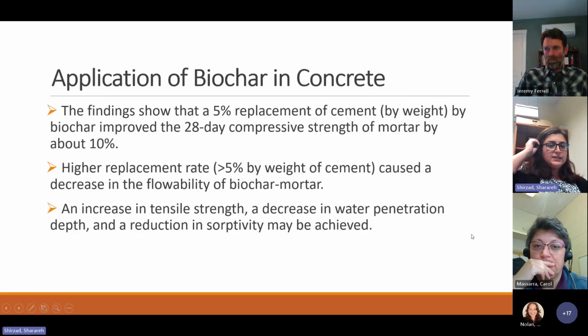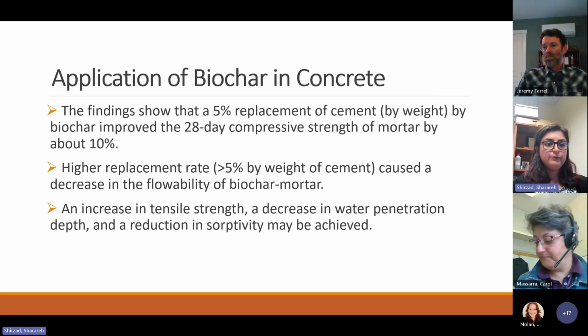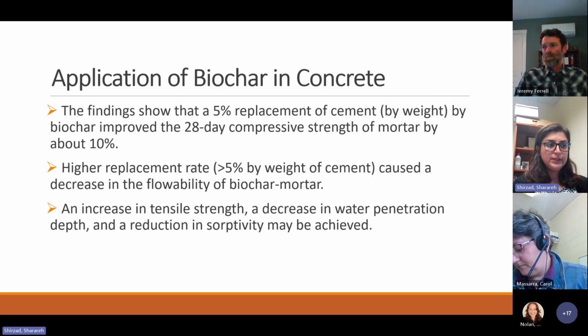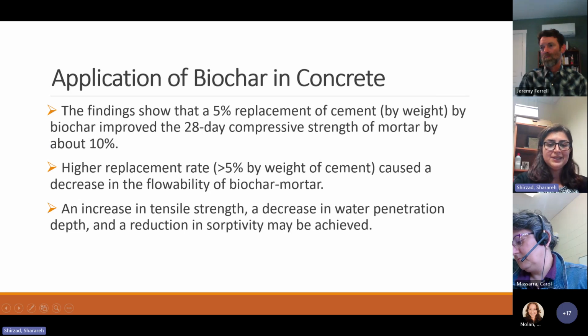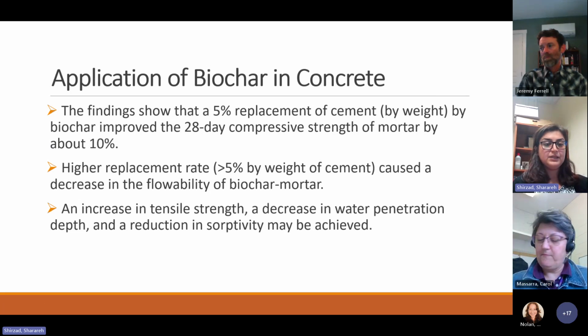So based on the previous studies, they showed that a 5% replacement of cement by weight with biochar improved the 28-day compressive strength of mortar by 10%. So we are doing 5%. That was the optimum biochar content based on the literature review, and that's the number that we are using in our study. A higher replacement rate, more than 5% of the weight of cement, caused a significant decrease in the flowability of biochar mortar. An increase in tensile strength, a decrease in water penetration depth, and a reduction in sorptivity may be achieved by using biochar to partially replace cement in concrete construction.